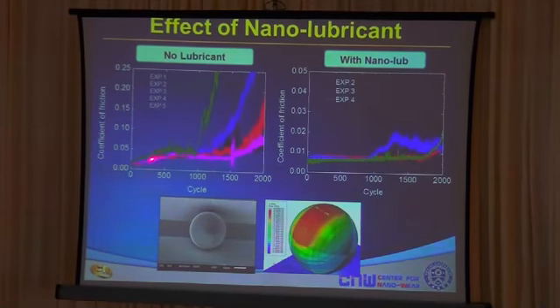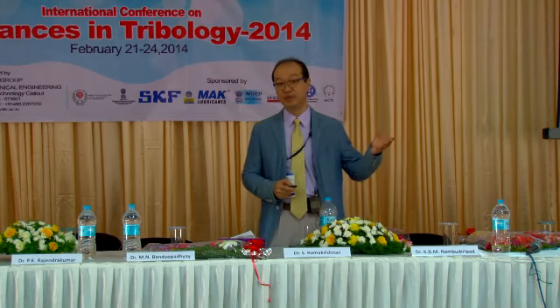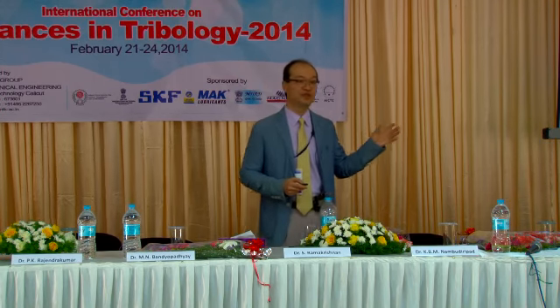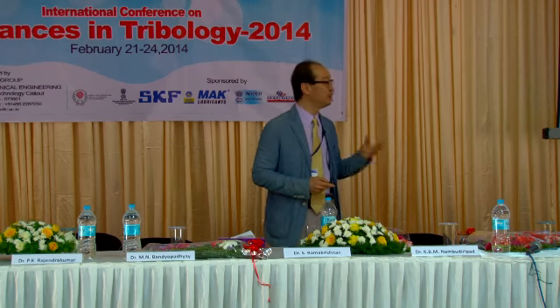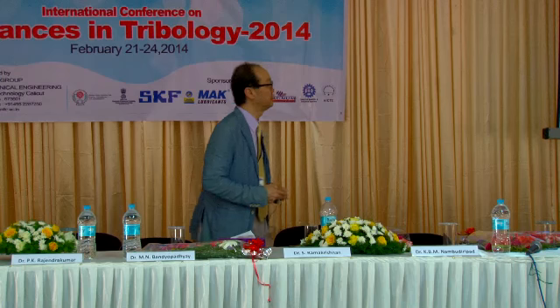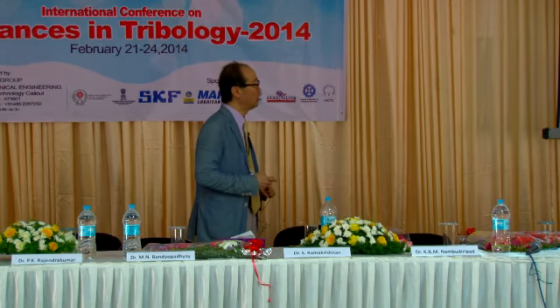Without the lubricant, you can see that the balls fail at about 1,000 cycles. But with the nano-lubricant, you can see that for repeated 3 experiments, we can maintain the friction coefficient relatively low up to a much larger number of cycles. Now obviously, we need further optimization to make this particular technology commercially viable, but nevertheless, we've shown the feasibility of using microballs for very small mechanical systems. So, micro-rolling bearings together with nano-lubrication is promising for micro-scale applications, would be my message to you.